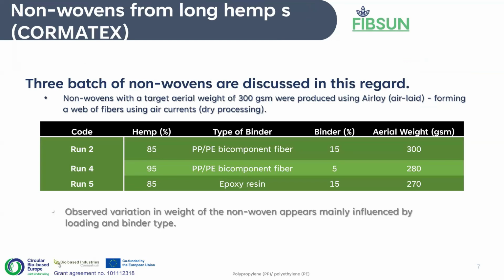So after we examined these base properties of our fibers, we applied the fibers in non-woven. This is an activity that was done by another partner called CORMATEX. What they did here was produce some batches of non-woven material, with a target area weight of 300 grams per square meter. In this case, we will talk about 3 batches of this non-woven. In 2 batches, they used the same binder, but different loading. In the first case, what I referred to as run 2 is non-woven with about 15% binder. In this case, we were able to achieve the target area weight. In the second case, you have non-woven with 5% binder amount, a slight decrease in achieving our target.